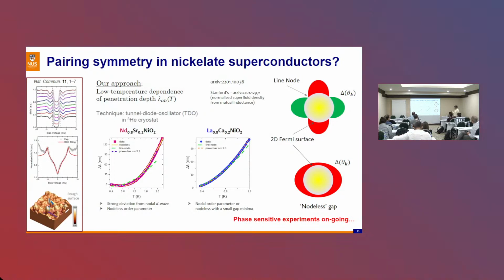Okay, so because of the limited samples, what we are able to do so far is London penetration depth, which is basically looking into the response of the samples as you apply a magnetic field, and the resonance frequency of the LC circuit. This difference in the change of the resonance frequency will be proportional to the change in the penetration depth at very low temperature. So we have to aim at very low temperature, so millikelvin, 100 millikelvin. And of course, the London penetration depth will be proportional to the gap of the system. You can look into the fitting and the power dependence of this, then you can classify whether something is related more to D wave or S wave or a mixture of D wave and S wave.